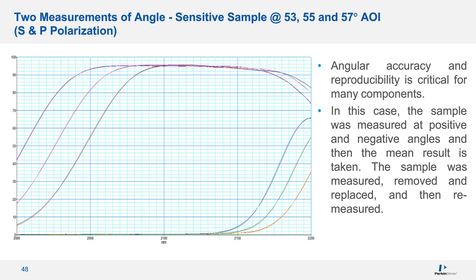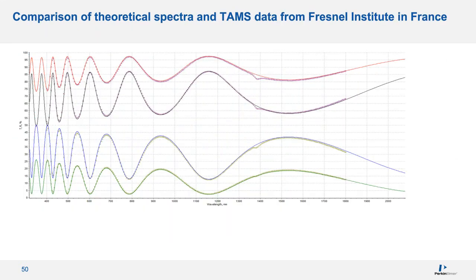Finally, in this case, we show a comparison of theoretical versus actual TAMS data provided by the Fresnel Institute in France. So we see here a combination of transmission and reflectance data for an unidentified sample. As you can see, the agreement between real and theoretical data is excellent.